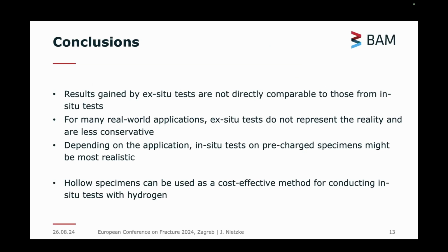Okay, and with this, I come to the conclusions. As we have seen, the results we gain by ex situ tests are not directly comparable to those gained by in situ tests. The same is true for the tests with electrochemical charging compared to gaseous charging, at least in this case, where we don't get a fully saturated material or uniform distribution.